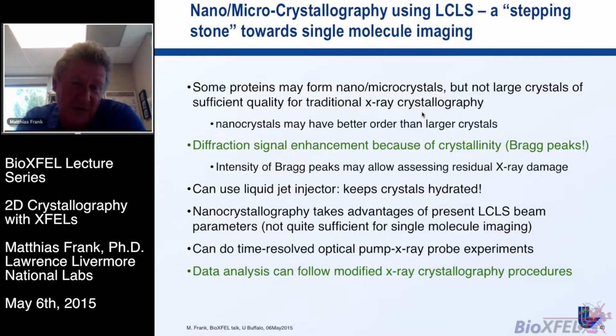So what I mean with using the intensity of Bragg peaks to assess damage is, if you know how large your nanocrystal is, you can calculate how intense a particular Bragg peak should be. And then as disorder sets in during the damage process, the intensity of that Bragg reflection goes down. So when you compare the measured Bragg intensity to the one that you calculate, you might get an idea how much residual damage may still be there.